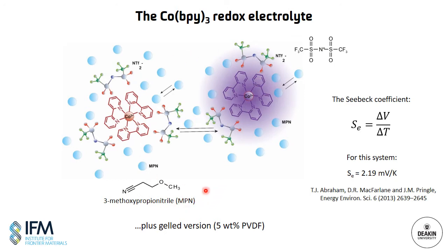And we're looking at both the ordinary liquid form of this electrolyte. We're also looking at a gelled version, which we make by adding 5 weight% PVDF. Now, this system was chosen based on its Seebeck coefficient, which is a measure of the amount of potential generated per unit of temperature differential.